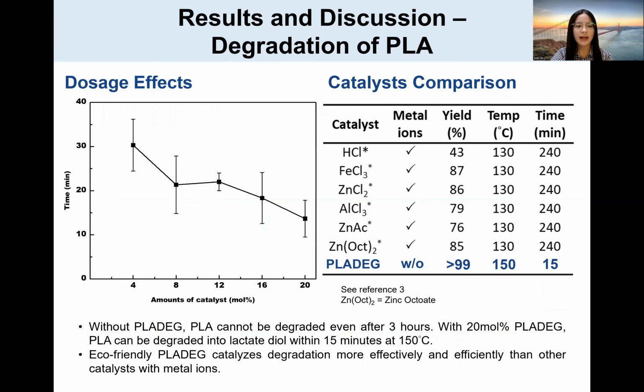So the graph on the left shows the dosage effect, which means the amount of catalyst will affect the time needed for complete degradation. PLA-DEG is critical for the degradation. Without it, PLA cannot even be degraded even after 3 hours. But with PLA-DEG, PLA can be fully degraded within just 15 minutes under 150 degrees Celsius.